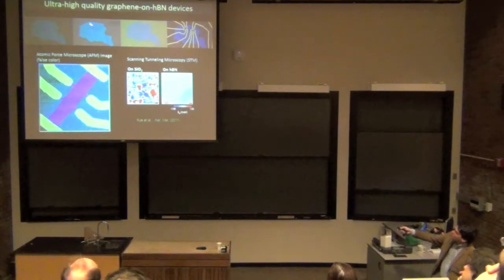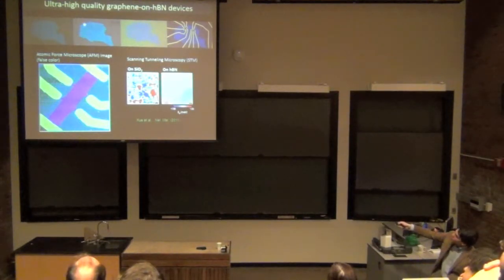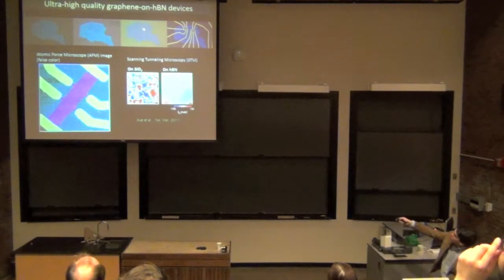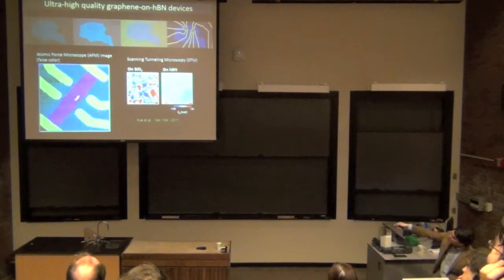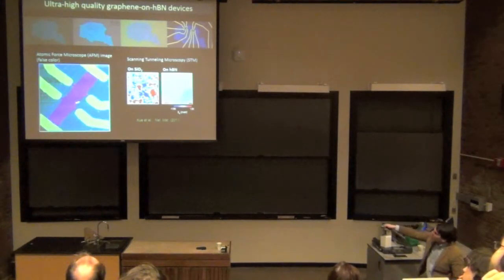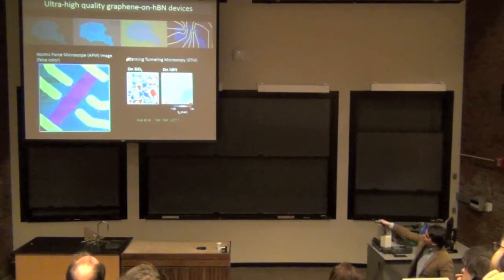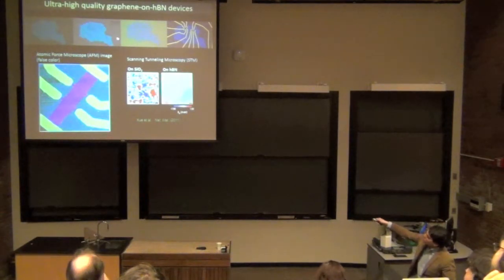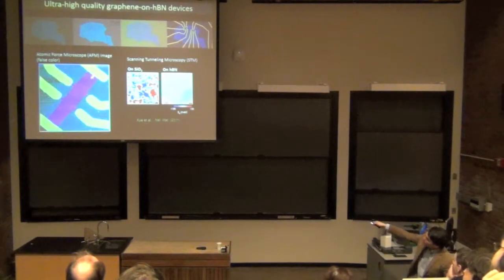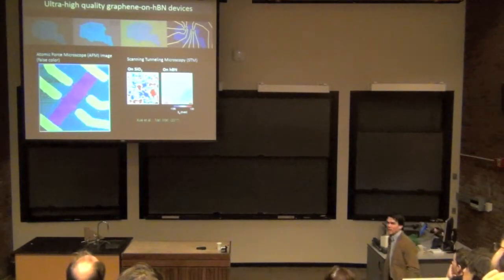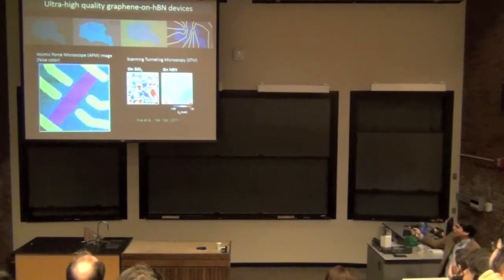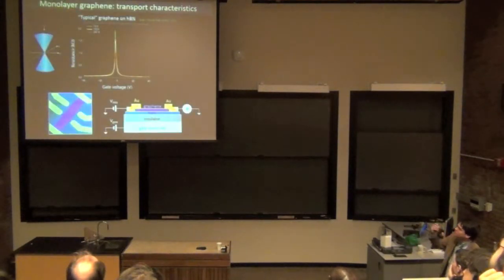And once we do that, here you can see it's a little dark here, but you can see pieces of graphene on boron nitride. We can etch devices out of them, attach electrical leads. And you can see how flat the graphene is here in this false color atomic force microscope image. And then maybe even clearer from the scanning tunneling microscopy image, you can see that on silicon oxide, which is a typical substrate for graphene, it's extremely disordered. When we place graphene on top of this hexagonal boron nitride, basically all of that disorder goes away. So this is what I meant by ideal substrate.